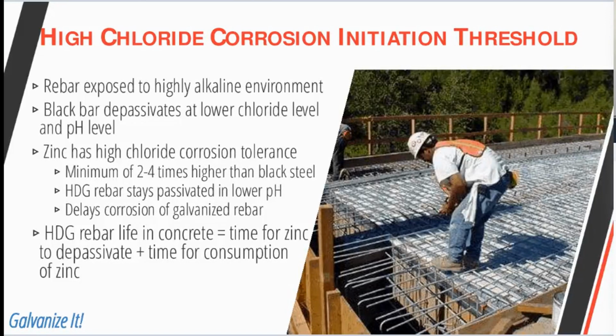And despite these advantages, there are often concerns about zinc's initial reactions in concrete because immersion in wet concrete is a really alkaline environment. And alkaline environments are typically not considered suitable for hot dip galvanizing. While this is technically true, attack on the galvanized coating stops as soon as the concrete hardens. And then that has a negligible impact on the design life in that short time period. Afterwards, the performance of hot dip galvanizing works differently in concrete than if it is just exposed to the atmosphere.